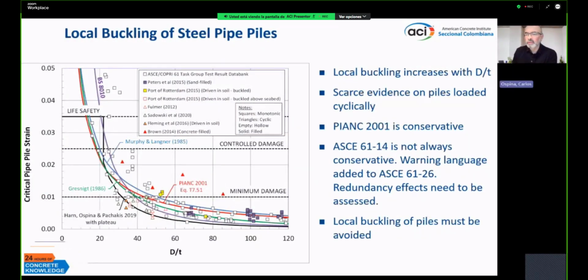When I mentioned local buckling, you need to be careful with the size of the steel pipe pile relative to its thickness. As the D/T ratio increases, the chances of local buckling increase. So you need to be very careful with defining the so-called critical strain. You need to be aware that the provisions in ASCE 61-14 are not always conservative, and there may be circumstances where you just can't achieve the target strains that the standard expects you to follow, especially for the life safety condition. You need to have a pile that is super compact to achieve those limiting strains.